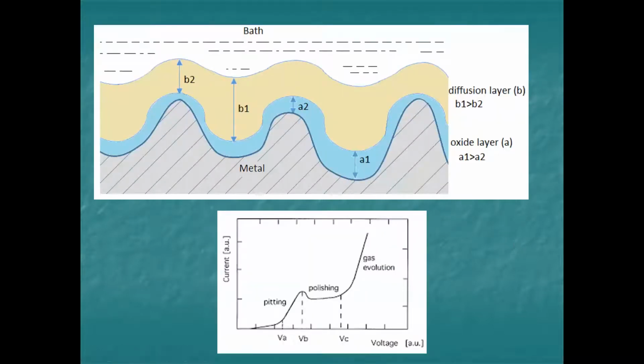Another thing to understand is, I mentioned a while ago that the electrolyte is not as thin as you might imagine. In fact, it's quite viscous. It's quite thick, in other words. And the mechanism which allows us to eat away the peaks of the mountains before we go into the troughs or the low parts can only happen if we have what's called a diffuse layer on top of the object. And this diffuse layer is actually a stationary layer. If you were to stir this in a tank, this layer, which is close on the surface, is so viscous or so thick, it doesn't move. It's what's called stagnant. So there's no convection in this layer here. So the only way material can go from the surface into solution is by a process of diffusion. And this diffusion process is critical in the electropolishing action.